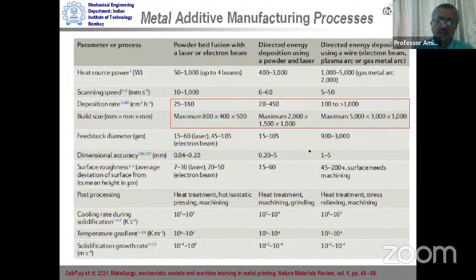Broadly, if we look at their capabilities, this table from this particular reference gives us some ideas about the capabilities of these three broad processes. I have highlighted these two lines, like the rate of deposition of feedstock material. With powder bed fusion, the deposition rate is around 25 to 180 cubic centimeters per hour, based on the openly available published literature. In comparison, directed energy deposition with a laser beam has a much higher rate of deposition. And if we move to the gas metal arc based process with a filler wire, we see the deposition rate is much higher. This is very important, as we will come back to these values later.